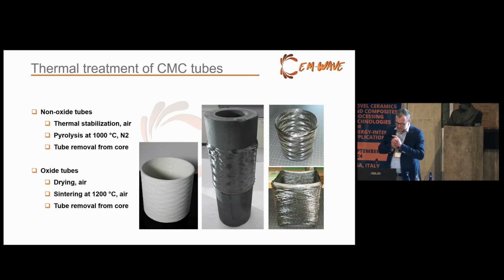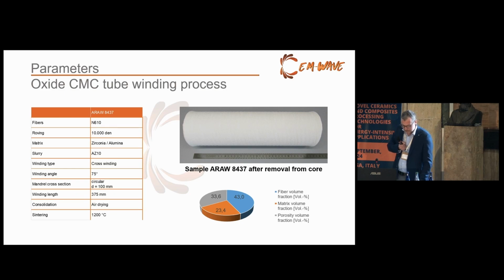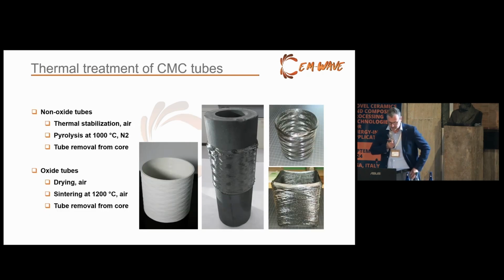And I always said we normally need to cut the edges because when we do some coating, or even when we want to have a denser matrix within the preform, you need also access to open porosities. But in this case, it was not so easy, so that's why we had to think about different ways. So we stabilized our very brittle silicon carbide preform with CVI silicon carbide, and then it was stable enough to cut the edges and do the final coating, which I described some slides later with the YAS system.